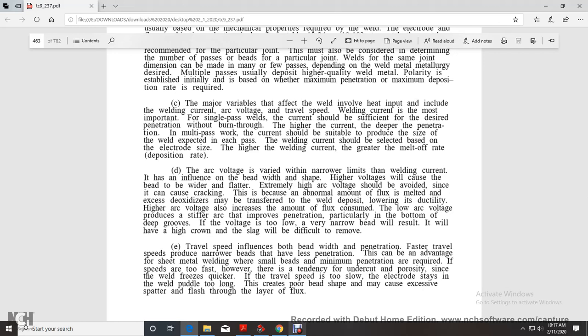Welding current is the most important variable. For a single pass weld, the current should be sufficient for the desired penetration without burn through. The higher the current, the deeper the penetration. For a multiple pass weld, the current is suited to produce the desired size of weld for each pass. The welding current should be selected based on the electrode size; the higher the welding current, the greater the melt-off rate and deposition rate.